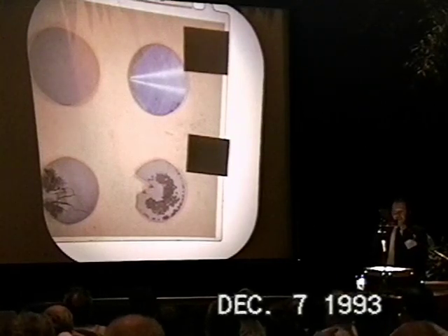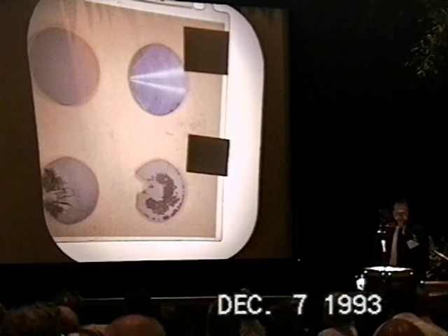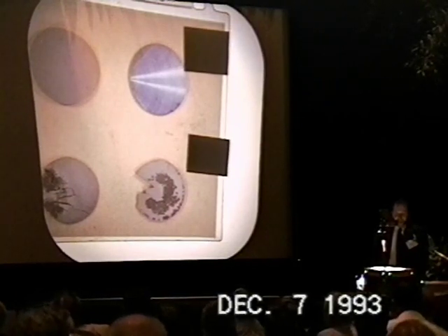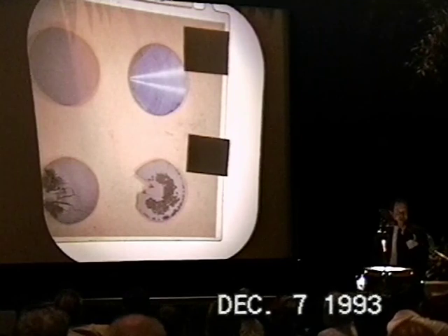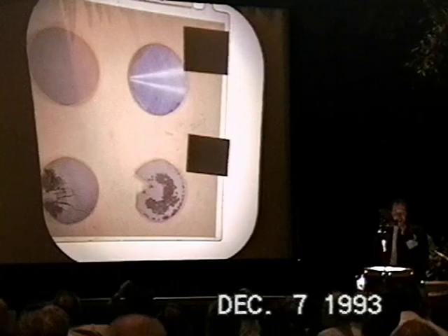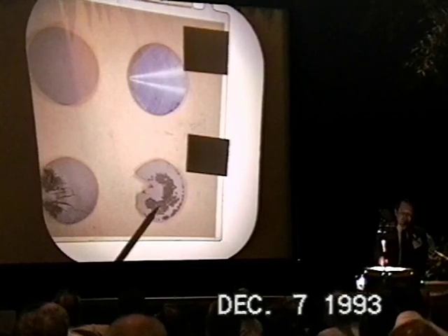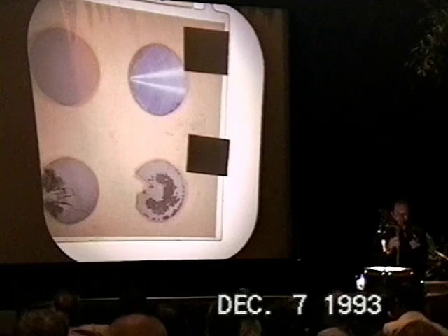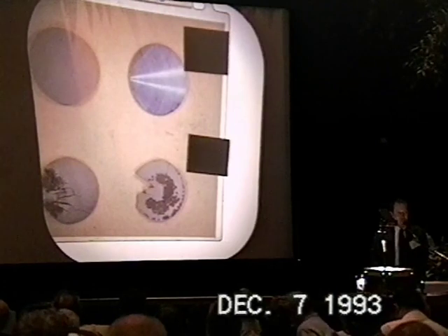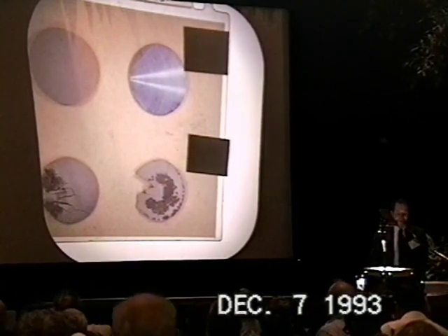Partly because of the difficulty you have producing these pressed powder cells, Tom does most of the pressing of powders, so he has the difficulty trying to make them reproducible. But also because of an increased interest, by us and among other people, that the effect may be due to current density. In many of the cells that were successful, we see things like this, these little arcing pits. That obviously would sometimes bring the experiment with high current density to a very small area as opposed to spread out over the whole cell.